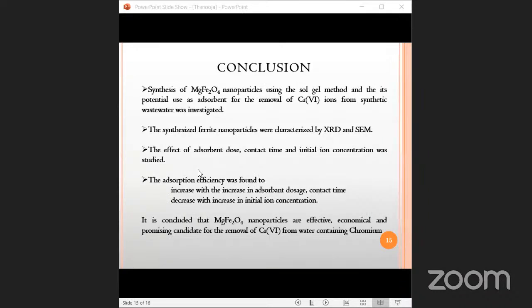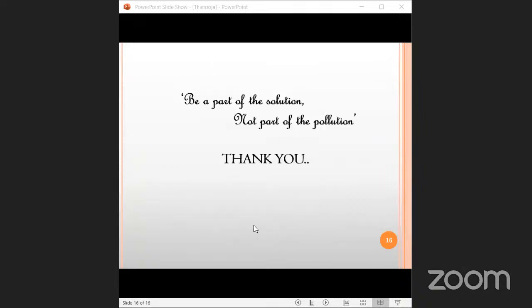And coming to the conclusion, magnesium ferrite nanoparticles were synthesized successfully using the sol-gel technique, and its characterization was done by XRD and SEM. The effect of adsorbent dose, contact time, and initial ion concentration was studied, and it was found that the adsorption efficiency was increasing with increase in the adsorbent dosage and contact time, and it was decreasing with increase in the initial ion concentration. And it is concluded that magnesium ferrite nanoparticles are effective, economical, and promising candidates for the removal of chromium ions from wastewater. Thank you.